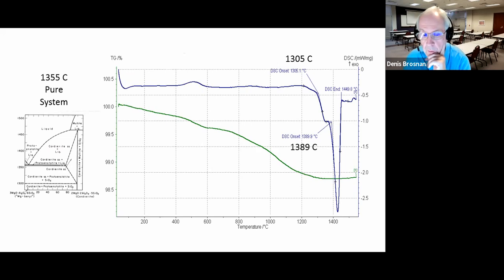Now, I decided to melt some cordierite. The blue line is a differential scanning calorimetry curve of what happens to cordierite in a crucible when you try to melt it. And right over here at 1305 degrees C, the cordierite that I had made, the computer identifies that as an inflection point. Okay, and it's pretty interesting that it shows an endotherm. Of course, melting is endothermic. Pretty quickly we get up here close to 1400 degrees C, and all of a sudden we're at the peritectic temperature.